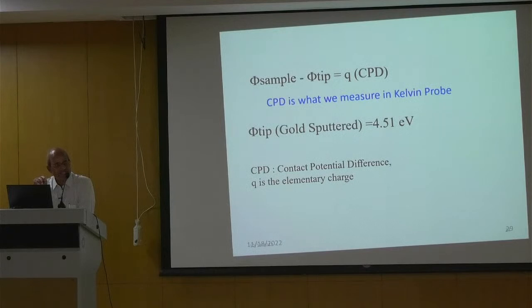What is this charge carrier concentration? This is the charge carrier concentration: how much charge has flown from sample 1 to sample 2 under the given conditions. So therefore, I can quantitatively say how much charge is transferred. For example, if it is your photocatalytic process, by shining light, there is a charge transfer process. So what is happening? Fermi level changes, contact potential difference changes. If you can measure that, you can find out how much charge has moved. This is exactly our problem in photocatalysis. If you can enhance it, your oxidation will go up. So our interpretation of the charge transfer process through Kelvin probe is one of the most powerful techniques.